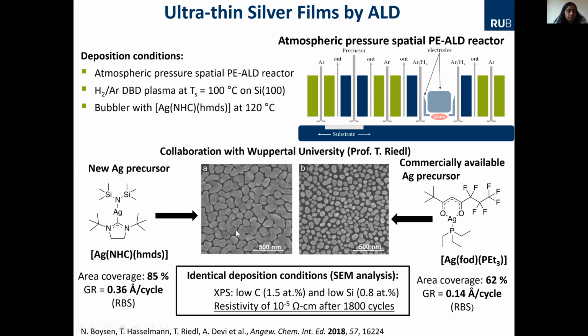They tested them under similar conditions, same substrate, same temperature, same flow rate, using the dielectric barrier discharge plasma, which is a mixture of hydrogen and argon, and then they varied the temperature of the vaporizer and the substrate. It's around 100 degrees centigrade. Again, you see it's a very low temperature. And then we looked at the surface coverage. With this precursor, you see some sort of grains. They're not well connected. And if you look at the SEM, the surface coverage is around 62% area coverage. And when we looked into the new precursor, we had higher coverage, okay?